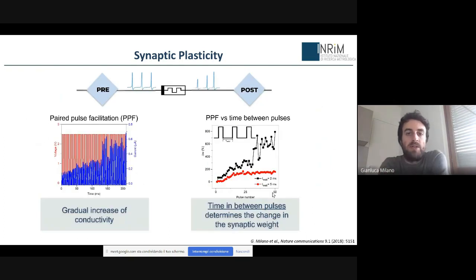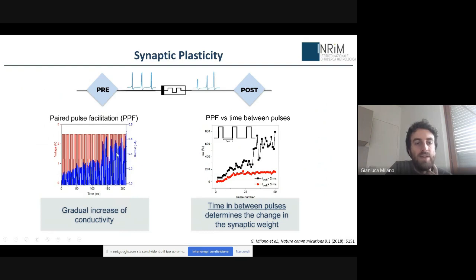And by exploiting this process, we can emulate some typical features of synaptic plasticity, such as paired-pulse facilitation. So what is paired-pulse facilitation? This is a rule in biological synapses that says that if two signals are temporally correlated, this will cause an enhanced transmission of signal. And this is an example. If we apply multiple temporally correlated pulses to a memristive device, we can see a gradual increase in the current that is related to a gradual increase of conductivity in an analog way. And of course, the time in between pulses is related to the correlation of the input signal.